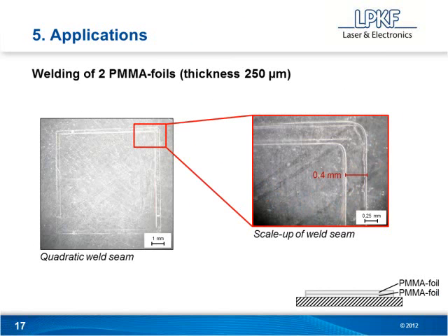So let's jump into a few applications, and these are just different material combinations that we've put together. A lot of these we're really just testing. Some of these took place in our lab in Germany, and then Tony, I'll have a few slides here at the end to show you with some applications and materials that he's welded in his lab down in Santa Clara. So in this case, we have just two PMMA foils, pretty thin, 250 micron thickness, and I have a little animation here. So again, you just get that volumetric heating through the part. So the weld zone is actually taking place throughout both pieces of plastic.